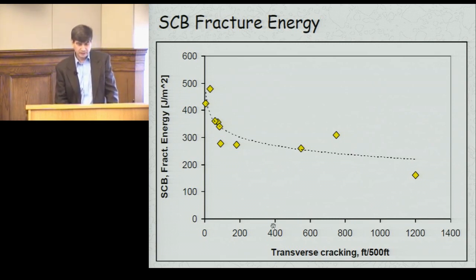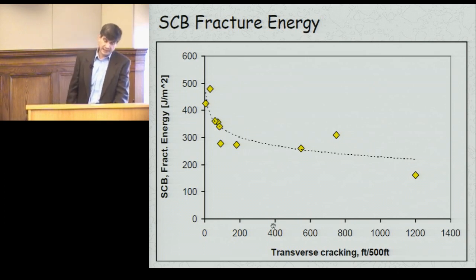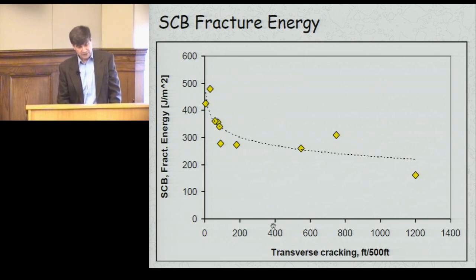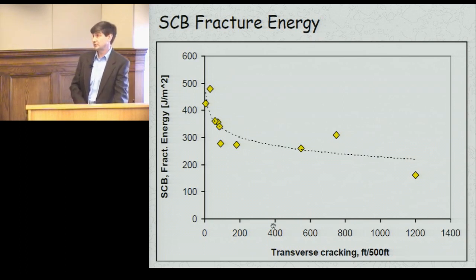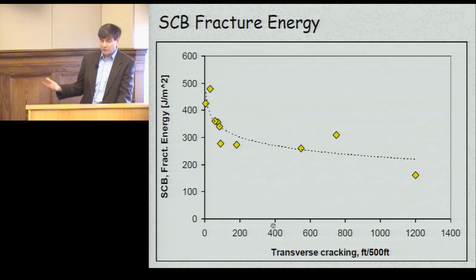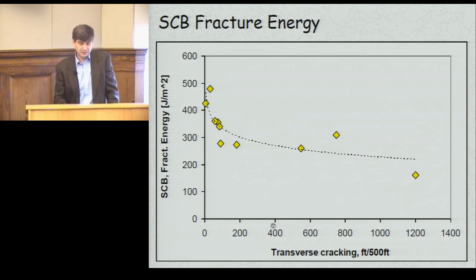If you look at this, on this horizontal axis you have transverse cracks in linear feet per 500 foot sections, and on the vertical axis you have, in this case, fracture energy obtained with the SCB test. As you can see here, it appears that, and the correlation is relatively high, that once you get into the 350 or higher, close to 400, transverse cracks actually start to almost disappear.